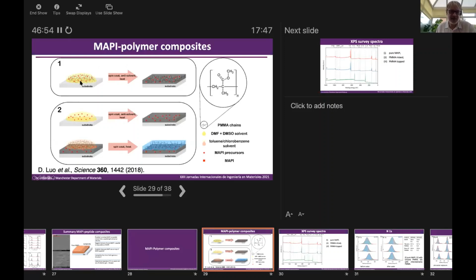The first one is essentially just to mix the MAPI with the polymethyl methacrylate in different solvents, and then spin coat onto a substrate. And the second was to form the perovskite layer and then add a cap of the polymethyl methacrylate in toluene or chlorobenzene.